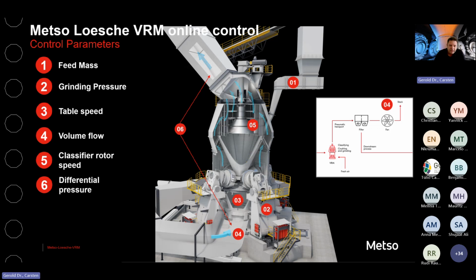The alternative is that if the ore is getting harder, it would accumulate, so your pressure drop would increase. There are different ways to respond. One is just to reduce the feed, but usually we would foresee some pressure reserves within the hydraulic piston system that basically pulls your grinding rollers down to the table. Therefore, by increasing the grinding forces, you will get more efficient grinding, or more efficient comminution. And then you can even stabilize your throughput, although your ore is getting harder. So this is a really very flexible system.